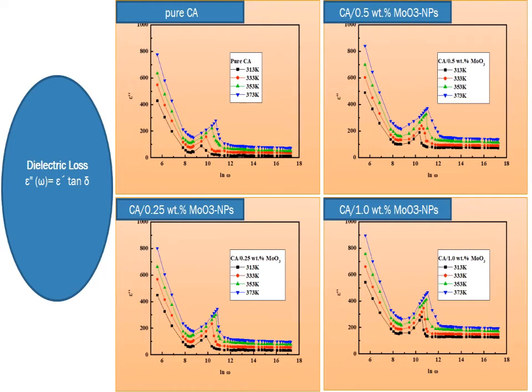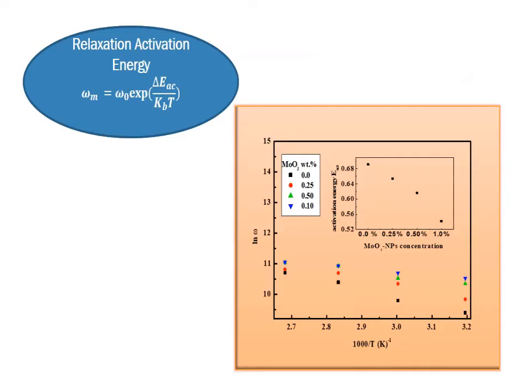From the higher frequency of the relaxation peak, we can evaluate the relaxation activation energy by using an Arrhenius plot. By plotting ln omega against the reciprocal of temperature, we can get the activation energy from the slope. In the inset figure, we drew the activation energy of relaxation as a function of molybdenum trioxide nanoparticle concentration, and we observed it decreases with increasing concentration of nanoparticles.